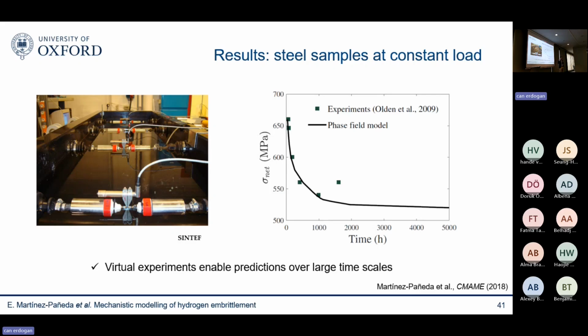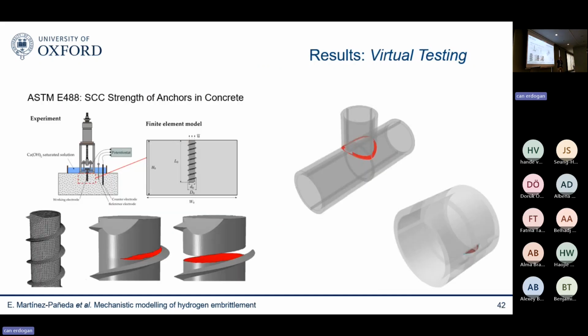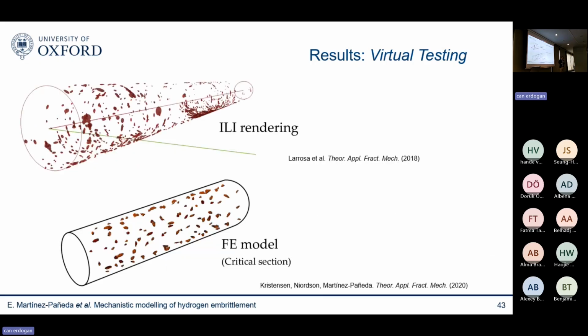But we can take the model and not only reproduce the experiments, but also run large-scale simulations over large time scales and predict this embrittlement region, the load below which you will not see embrittlement. So again, at the end of the day, this is a multi-scale informed, but macroscopic continuum model. So it's easy to run those kinds of large-scale simulations. And this is something that we have exploited to bring this idea of virtual testing to the hydrogen energy sector. Because with these continuum fundamental models, we can solve problems of any dimension and choice. And these are some 3D problems that we have shown here. In fact, we can also create some sort of digital twins of critical infrastructure.